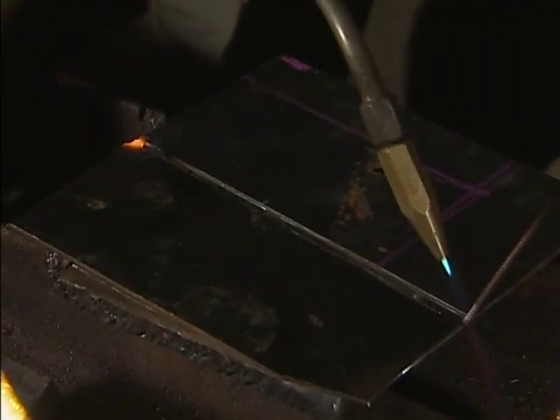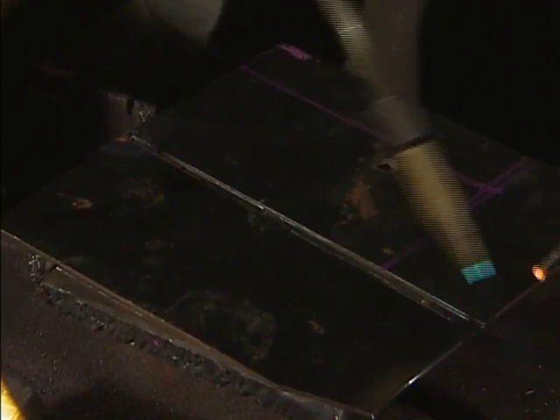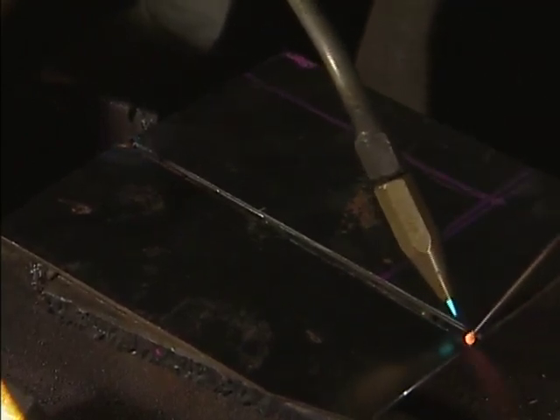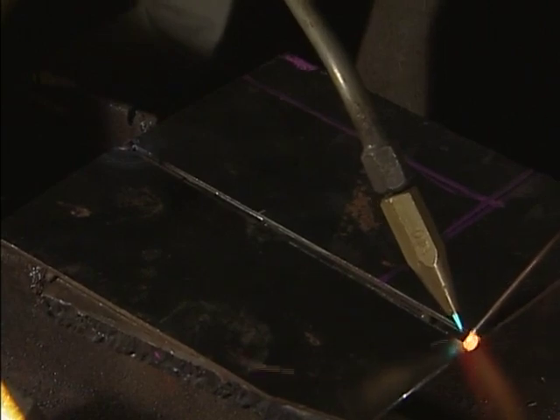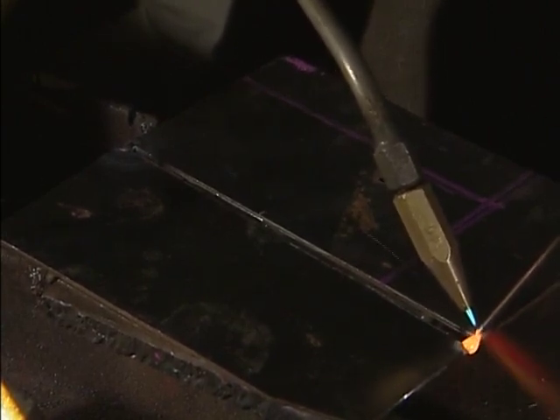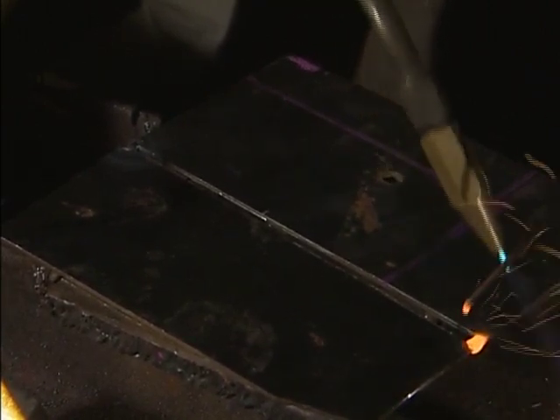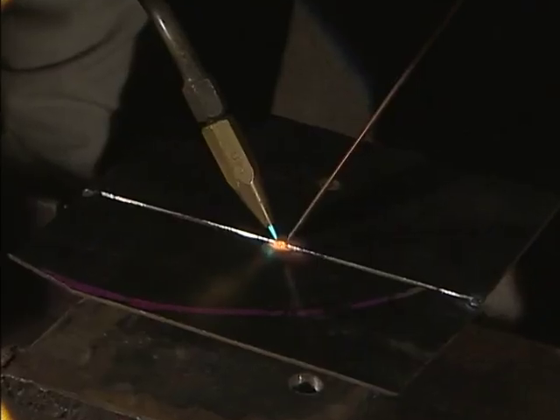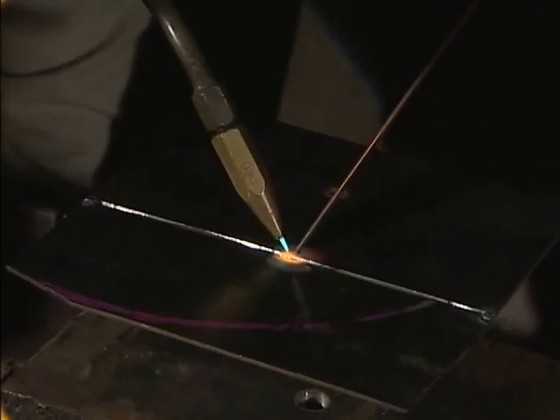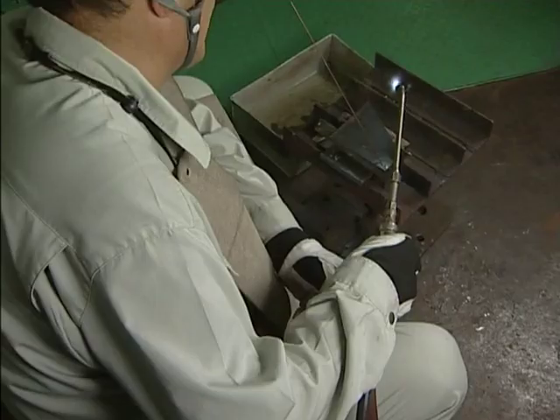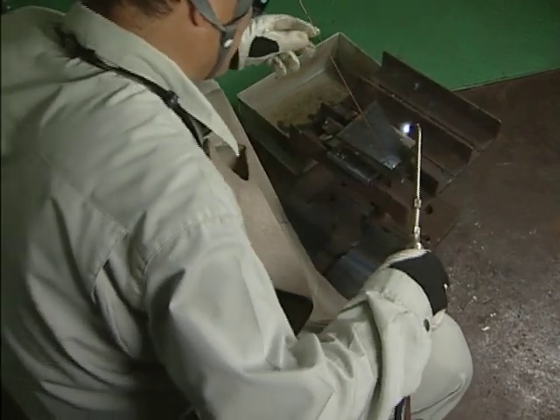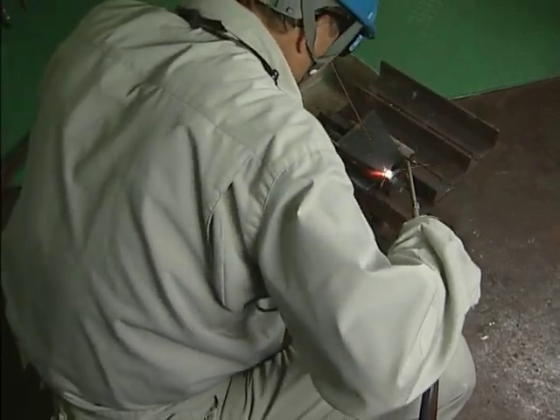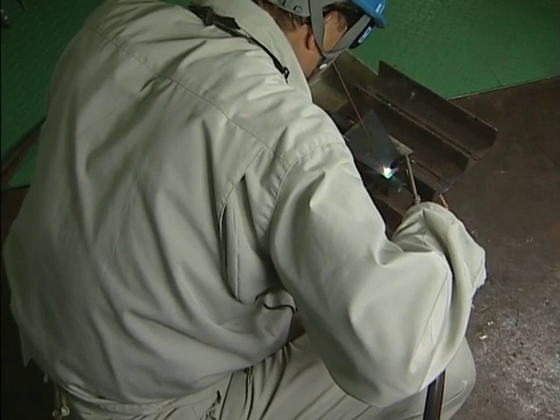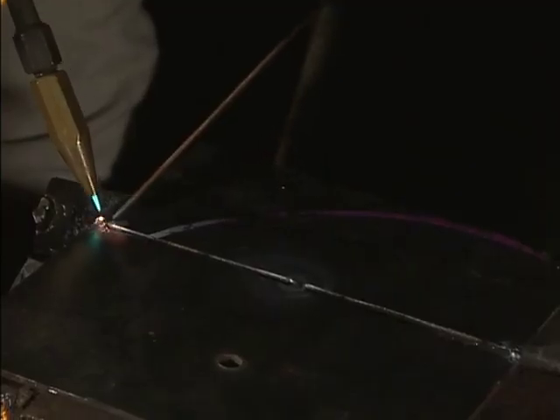Now we'll show you operations for flat position butt welding of thin sheets. Prepare 2 pieces of 2 mm thick steel sheets. Keep a distance of 2 mm or less between the 2 plates and provide tack welding at both ends and at the center as shown here. Weld from right to left, a method known as push technique.